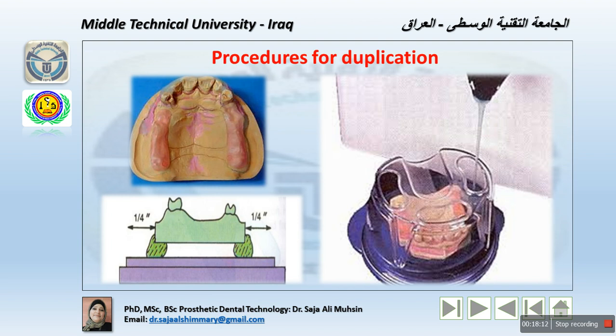The second thing is to fill all pores of the stone cast and displace trapped air, by placing it under a bell jar and activating the vacuum for 2 minutes. This is essential to remove all the pores that we have in the stone. Otherwise, what would that lead to? It leads to the agar-agar going into these pores within the cast, and this will affect the smooth surface of the duplicating material. We can have a rough surface on the refractory casts with nodules due to the pores of the stone, which withdraw the agar-agar into them.